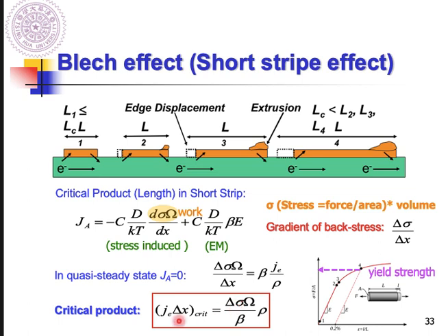So now we know, for the current density part, as long as you know this interconnect is responsible for which microchips, then you already for sure know the driving current density. So under this case, you can directly get the delta x is LC. What's the maximum length or critical length for this material or interconnect? Under this case, for example, it would probably be like 200 micrometer.